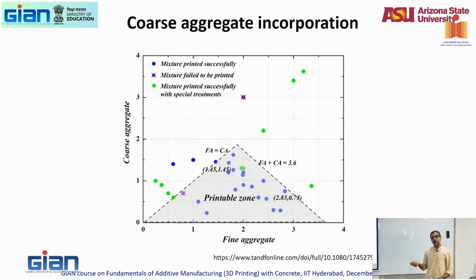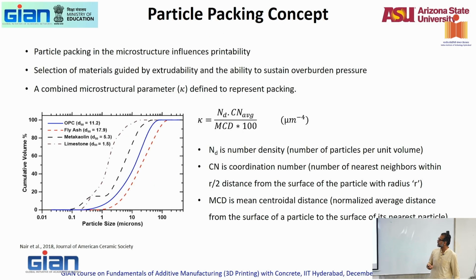Now, coarse aggregates incorporation. You can incorporate coarse aggregates. When they say coarse aggregates, it's typically less than 10 millimeters. You're not talking about 1-inch aggregates. No, none of that. Less than 9.5 mm aggregates. And so there's a certain zone in which you have a coarse to fine aggregate ratio that you can print, which is a function of your mix optimization, particle size, and all of that. And you can look at that.